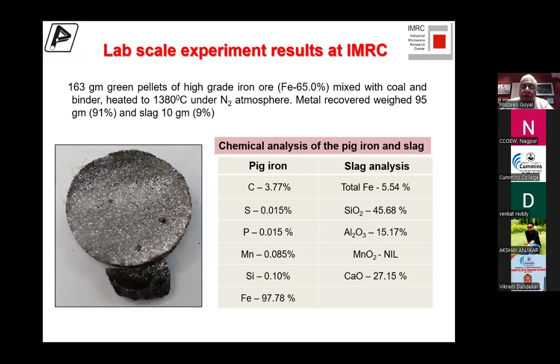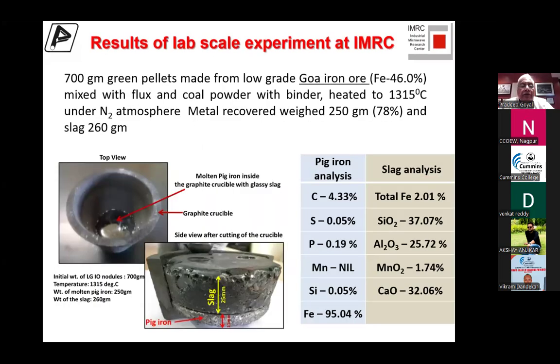So this is the configuration and the analysis of the iron that we were able to produce in a small scale furnace initially, with low sulfur, low phosphorus, a decent amount of manganese, and 97.78% of iron, which is quite good, and we recovered the carbon. So we were able to make very good quality pig iron.